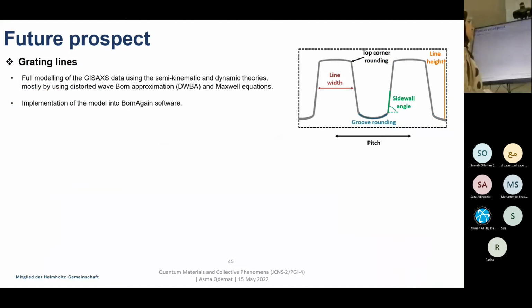For the grating lines, we concluded that there is no correlation between the grating lines and the arrangement of the nanoparticles, because up to now we could not understand the exact shape or geometry of these lines. Therefore, in order to understand this geometry, I'm now trying to fully model the GISAXS data of these lines using semi-kinematic and dynamic theories, mostly the distorted wave Born approximation (DWBA) and Maxwell equations, where I have to take into account several parameters like the sidewall angle, the top corner rounding, the line width, the line height, and other parameters. After that, the model will be implemented into the BornAgain software.